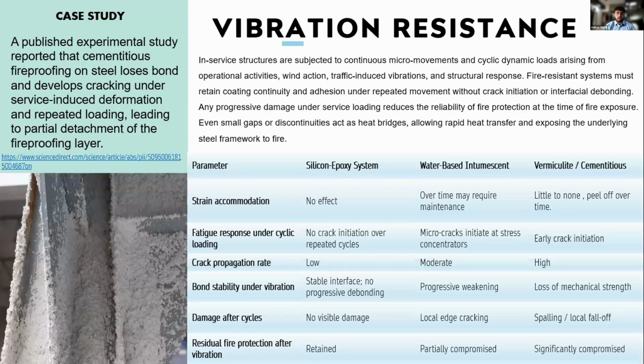Then we shall move on to the vibration resistance. Here I have attached the case study for this as well. A published experimental study reported that cementitious fireproofing on steel loses bond and develops cracking under service-induced deformation and repeated loading, leading to partial detachment of the fireproofing layer. So what that means is that we have tested this by creating a cyclic motion again and again to replicate the vibration made in a building over years.